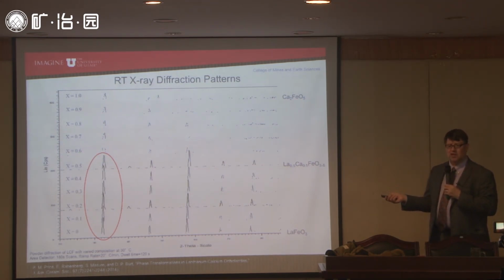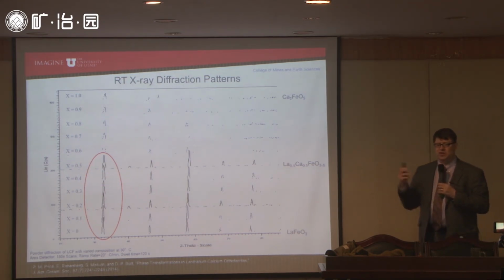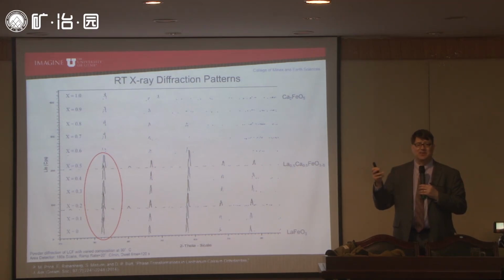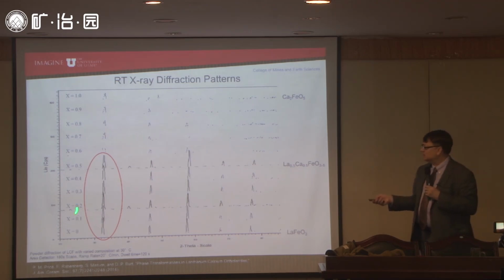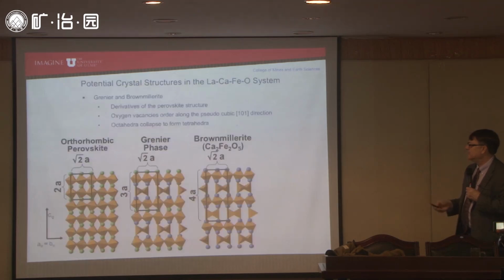Turns out that's wrong, and we figured out it was wrong pretty quickly, because even though we had these similar X-ray diffraction patterns, when you look at the microstructure, you can see evidence of a second phase, and so that didn't make a whole lot of sense. People in the literature had reported this and also seen a second phase, but never questioned it, because they believed their data. They believed one set of data, and again, proof of a mechanism is less like a mathematical proof than it is like a proof in a court of law. All right, so here's the thing.